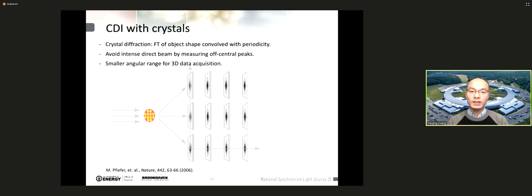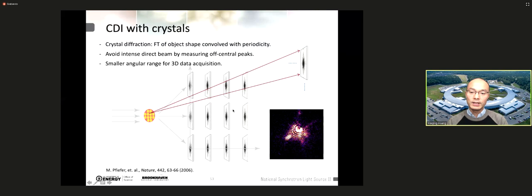And now, if your sample has crystal structure, besides the scattering pattern in the transmission direction, we also have identical copies at the Bragg peak locations. And in this case, we have another choice. We can place a detector to capture one of the Bragg peaks, and then we rock the sample. In this case, we only need to rock the sample in a 1 or 2 degree range to cover the entire 3D data volume,